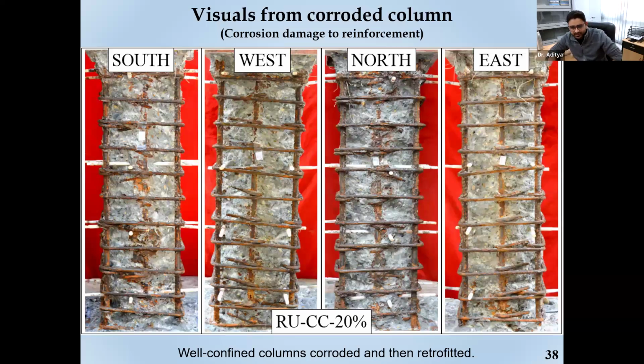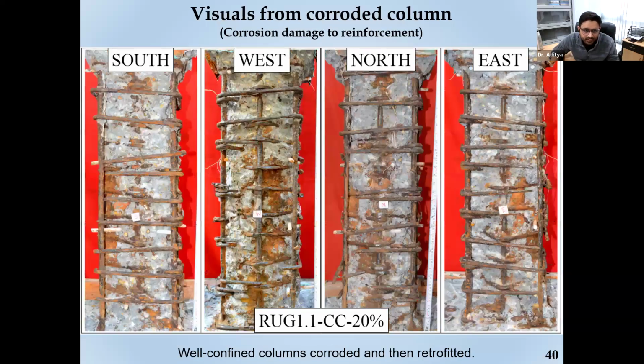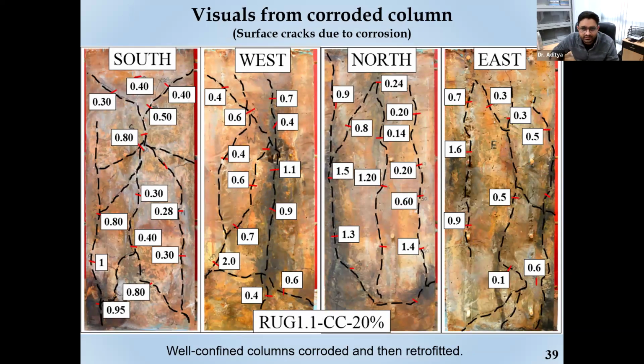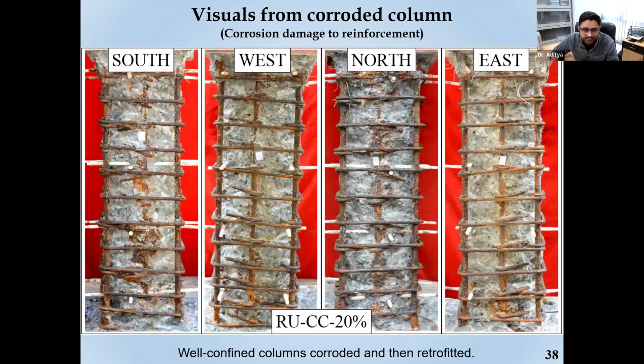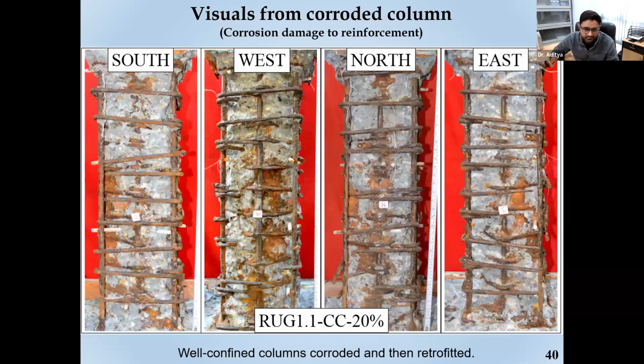And these are the visuals of the reinforcement of the 20% column. So this is a 20% column, RU-CC-20%, and that is another 20% column. You can see the visuals of them are very different. Both of them are 20%, but this seems to be more severe. That's what I was trying to say, that you do not have any control over the distribution of the corrosion. It can be distributed across the entire test length, or it can be concentrated more in a given domain. So you do not have any control over that.